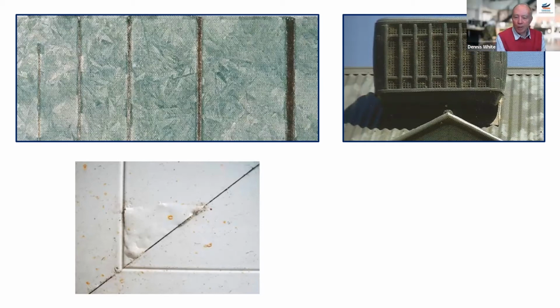There's no really long-term option. Your metallic surface, once it's breached to the extent that you're getting extensive rust starting to form, you've got to get rid of the rust. You've got to use a rust converter, and the jury's out as to how effective those conversion coatings or compounds are. And in themselves, they can create yet a further corrosion because they're basically an etching material, which can damage your surface a lot more. In extreme cases, you could try and metal spray zinc coating, but it's expensive and it doesn't really work that well.